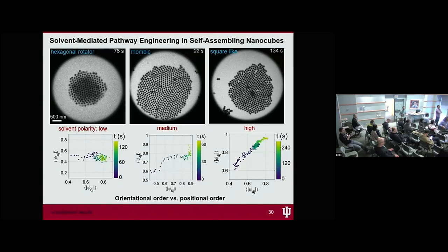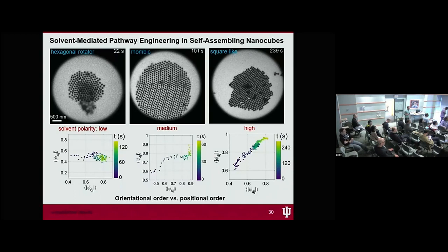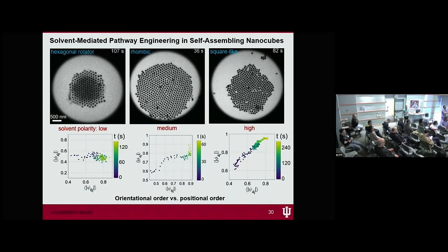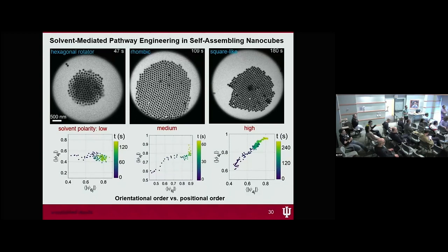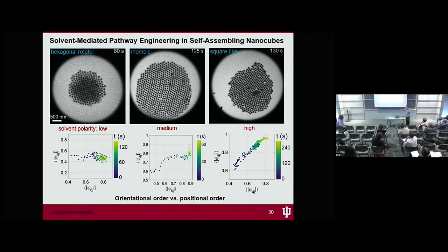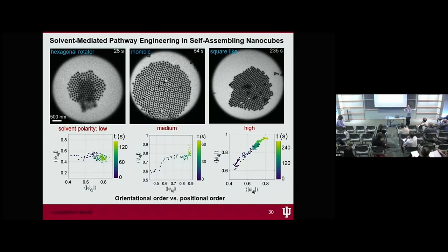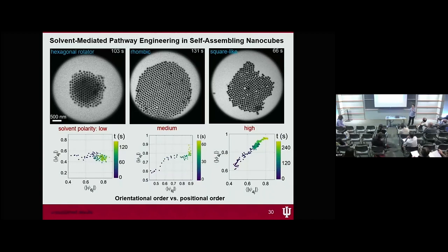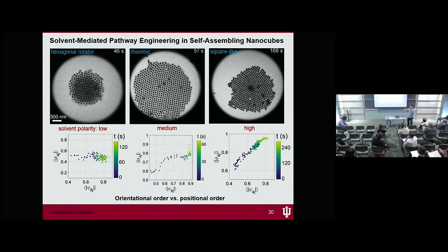Yeah, that's a great question. We actually spent a lot of time thinking about it while we were doing this research. The reality is when you illuminate the sample, both the silicon nitride membrane and the particle become positively charged. That's a generally agreed upon scenario. So there's not only particle-particle attraction laterally, there's also particle-membrane attraction or repulsion in the vertical direction. By changing the solvent, by controlling the medium, you can control the electrostatics and the overall interaction between the particle and the membrane.